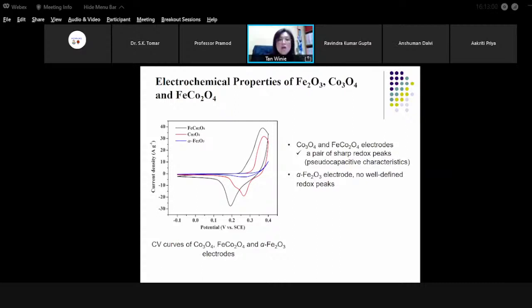So here are the CV curves. You can see here the red and also the black one. The CV curves for both cobalt oxide and iron cobaltite show a pair of redox peaks. However, in contrast, the well-defined redox peaks are absent for the hematite. The occurrence of the oxidation and reduction peaks is due to the Faradaic reactions. So this suggests the pseudo-capacitive behavior of cobalt oxide and also the iron cobaltite. The hematite does not show any pseudo-capacitive behavior.